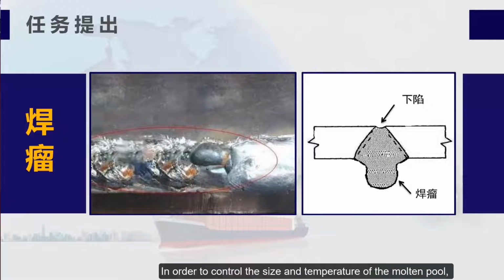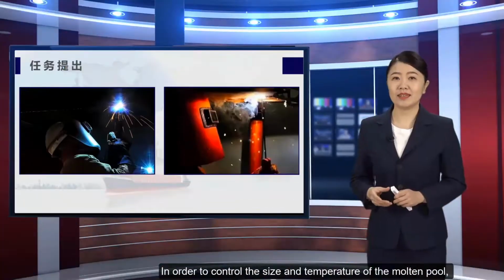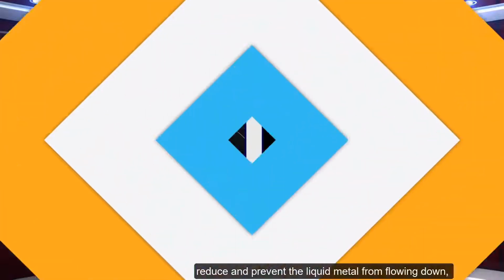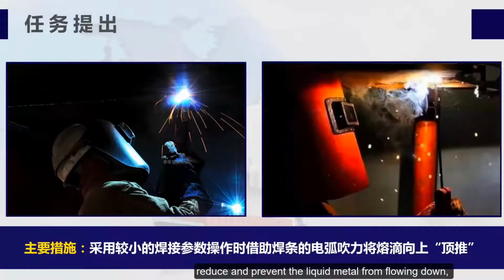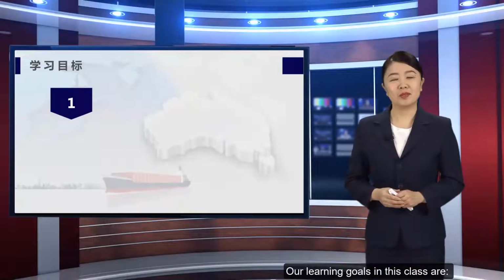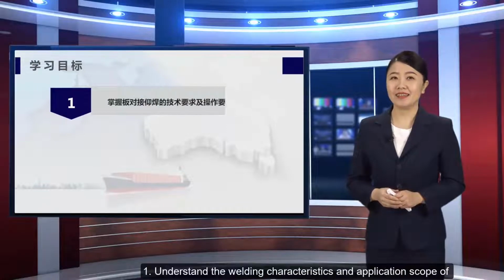In order to control the size and temperature of the molten pool, and reduce and prevent the liquid metal from flowing down, in addition to using smaller welding parameters, the arc blowing force of the electrode should be used to push the molten drop upwards. Our learning goals in this class are: